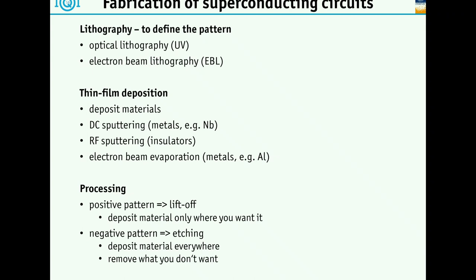So with that mask, we can then do a thin film deposition of the materials. There's different ways of doing that. You can use an electron beam to heat up your metal. It evaporates and gets put down. You can have different sputtering techniques. And all of that creates the thin films we then use.